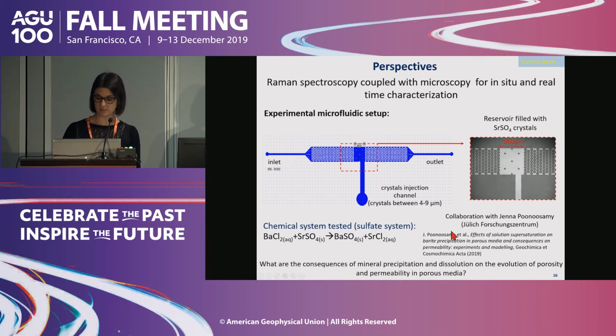So this work is based on a paper by Jenna Poonoosamy in Jülich in Germany. In this paper, they did some column experiments where in the column they have strontium sulfate crystals, and then they inject barium chloride. So they will dissolve the strontium sulfate, and then we will have barium sulfate that will precipitate. And because the molar volumes of strontium and barium sulfate are different, we expect a decrease in the porosity and a change in the permeability. What they observed in this work is that, first, the Kozeny-Carman equation that relates porosity and permeability underestimates the permeability change. And they concluded that they really need to take some pore scale processes into account in microscale models.